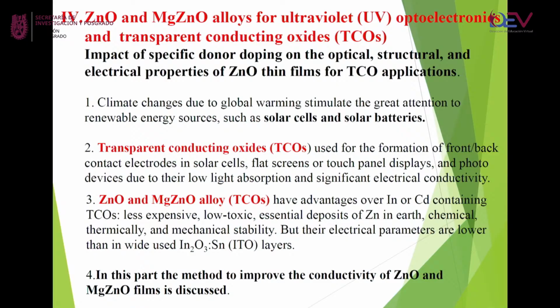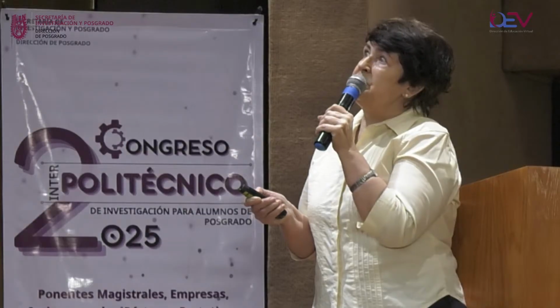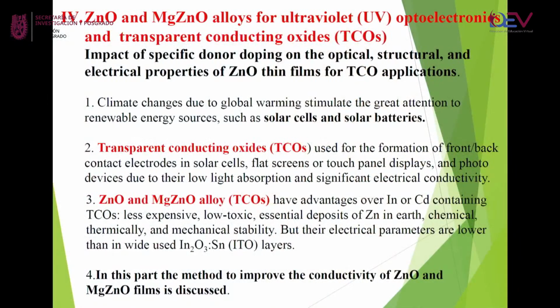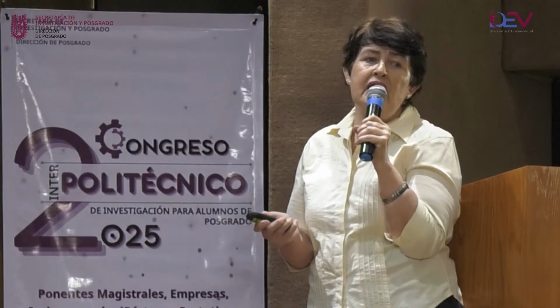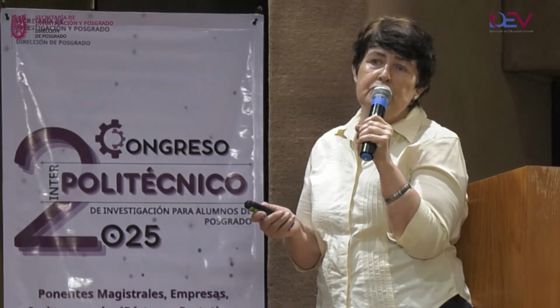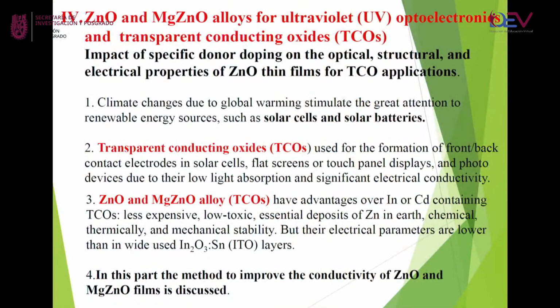And for this, to increase conductivity, different doping impurities were used. But nevertheless, up to the moment when we started to investigate this material, the conductivity was low in comparison with the conductivity of a widely used material, such as ITO. This is indium oxide with tin. So our task was to increase the conductivity of the transparent conductive oxide.